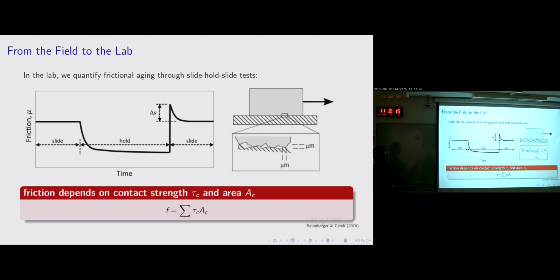Friction is kind of a broad and elusive term, but if we think of what exactly friction is, we know that every contact, whether it's nominally flat or polished, will always exhibit some roughness at some small scales. So even this seemingly flat contact would feature this topography where we have peaks and valleys, and the top solid and the bottom solid actually interact and touch through these topographic maxima. We call each of these contacts an asperity junction, or asperity, because each bump is an asperity.